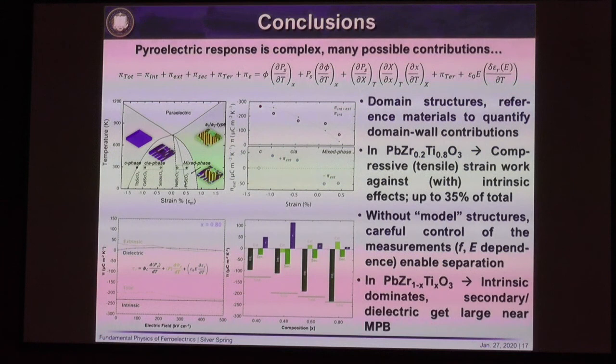Yeah, so I buzzed through it quickly, but there is a frequency dependence to the caloric power as well, right? Okay. So the power is on 2 omega. There's additionally a resonance in that system as well. So we can get the Joule heating and the electrocaloric heating convoluted at one frequency, but you can go to higher orders and you can actually separate out these frequencies, so these contributions.